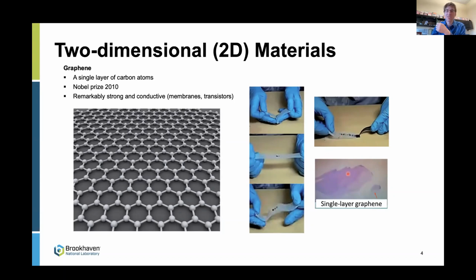And if you're lucky, again, you can transfer some of those flakes onto the substrate, and you peel off the tape. And again, if you're lucky, you'll be left with some really nice, clean, large flakes of the material you're interested in. And if you look around on the substrate, you'll find areas where they're really, really thin. They won't all be monolayers, but you'll be able to find some areas where they're monolayer. So if you're doing graphite, you'll find some areas where the flake is so thin, it's one atom thick, and that's graphene. The point I'm trying to make here is it's incredibly easy to do, which is cool. It's good that you can in just a few minutes make an atomically thin material. But as I kept saying, it's relying on this statistical notion of getting lucky, which is one of the downsides, right? You're really relying on the statistics of do it enough times and eventually you'll get the flake that you wanted.